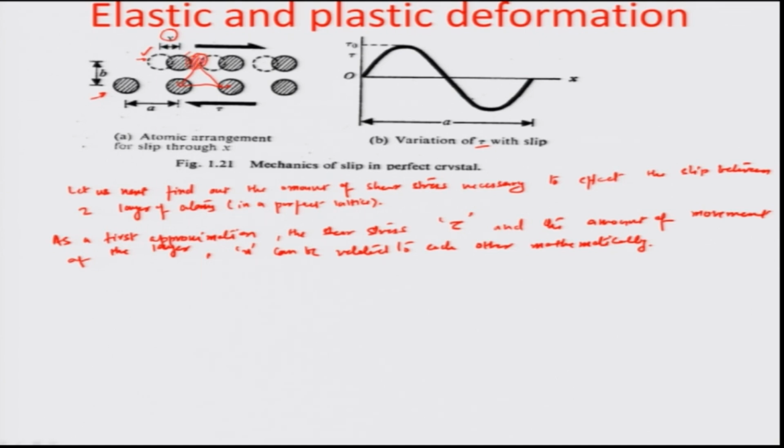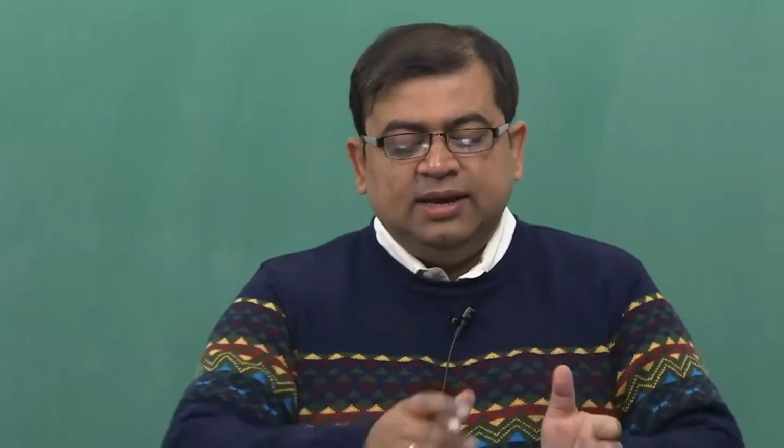So, the position here again has 0 forces, and the position in the center from which it started had 0 forces, and in between there are going to be some forces where at least halfway through this whole atomic movement by a lattice spacing A, there should be a force getting it back to the previous position, and for the latter half of this A there should be a force which would get this atomic system to the later position.